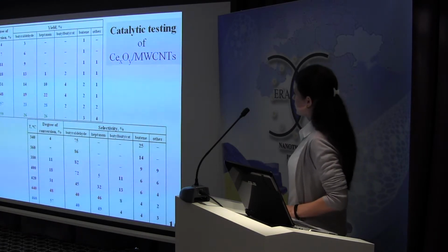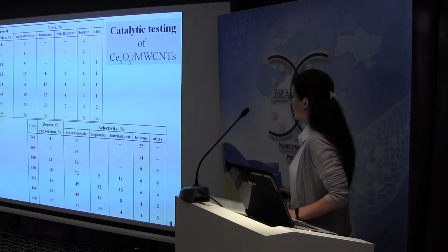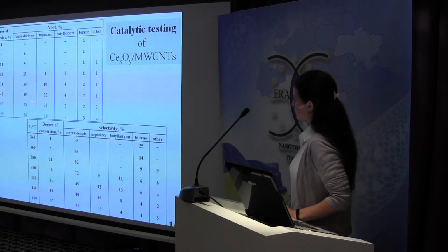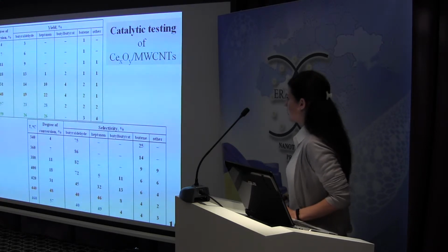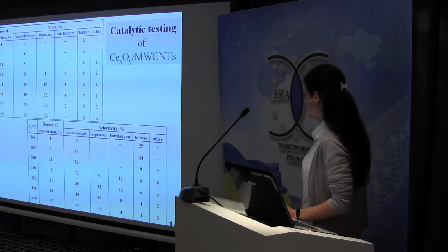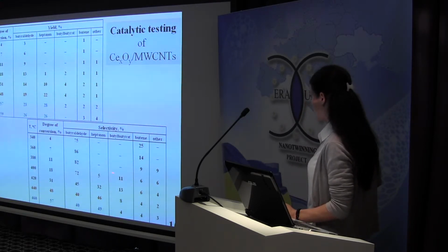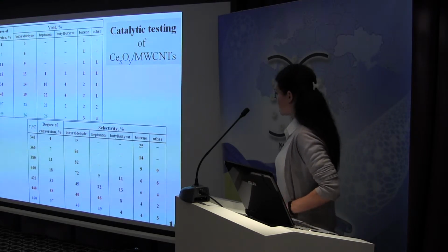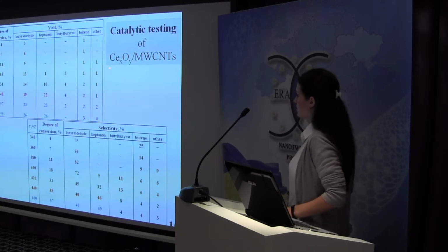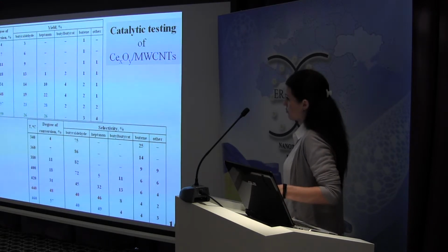Among the products of the reaction, we obtained butyraldehyde, heptanone, butylbutyrate, butane, and other products. The highest yield of butylbutyrate, butyraldehyde, and heptanone is at a temperature range of 440 to 480 Celsius degrees, and the highest selectivity of the catalyst to these components is manifested. Yield of other products is slight in the whole temperature range and practically unchanged, so we can ignore them.